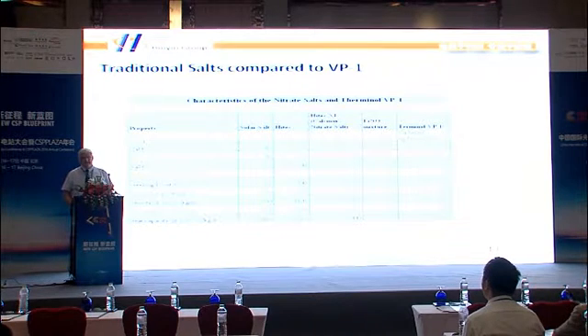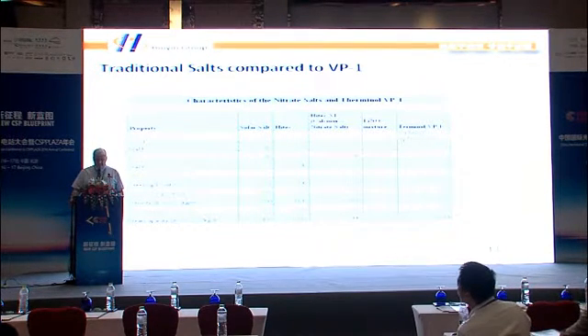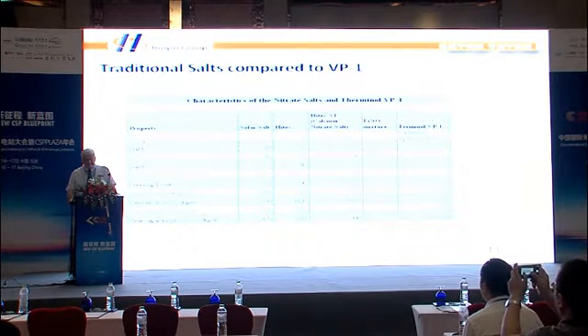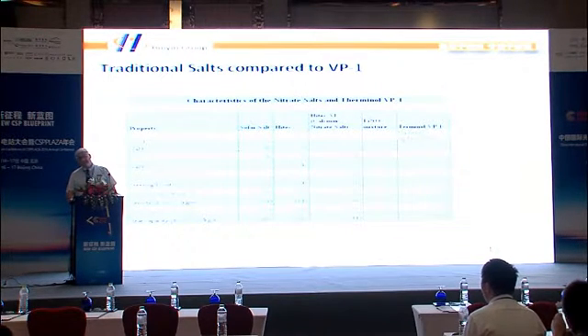Now if you look at the salts, because we are talking about salt, there have traditionally been quite a few salts on the market. There has been the binary mix, and there has been Hitec and Hitec XL. The binary mix has a pretty high freezing point. It freezes at about 220 degrees. To keep that fluid all through the night is not easy, certainly not in a situation like in China, where you have pretty cold winters, minus 30, minus 40, with strong winds. It's going to be difficult. So we do need a molten salt that has a lower freezing point.